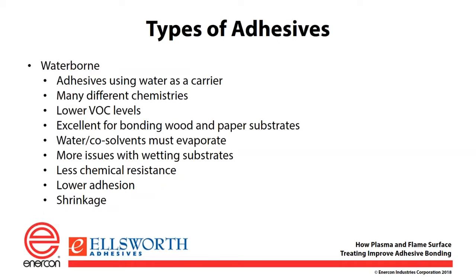Waterborne adhesives use water as a carrier. There actually still is solvent present. They're called co-solvents. This type of adhesive can also be done with many different chemistries, including epoxies, and there are waterborne polyurethanes. They're lower in VOC, and that's because water is not a VOC, but the co-solvents present generally are, unless you're using one that's exempt. These are excellent for bonding wood and paper. They can also be used on many other substrates. However, they tend to have more issues with some of the other substrates.